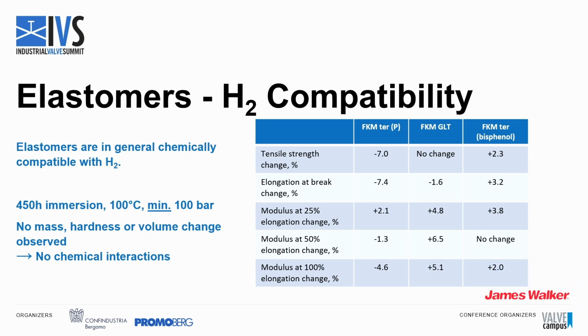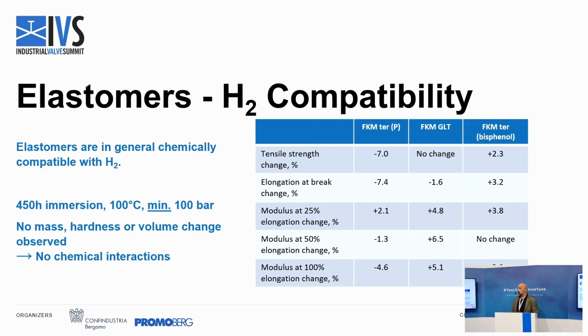The point is that during this test, and I underlined the minimum 100 bars, because we saw that we had to repressurize during the test, which means that somewhere this hydrogen somehow entered in the elastomer chains, in the elastomer compound.